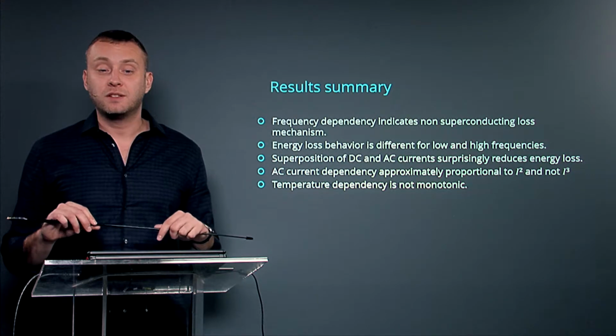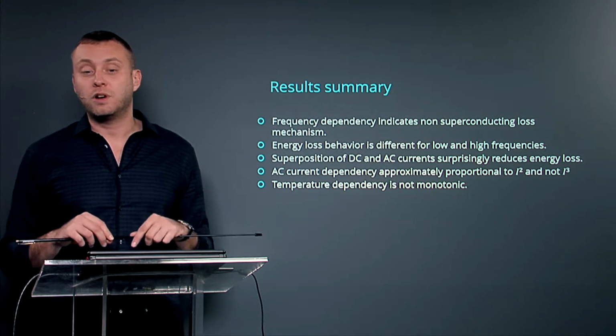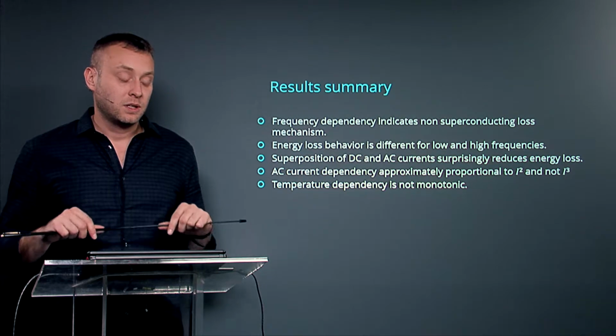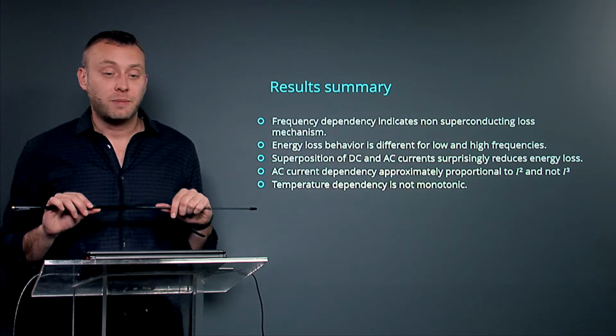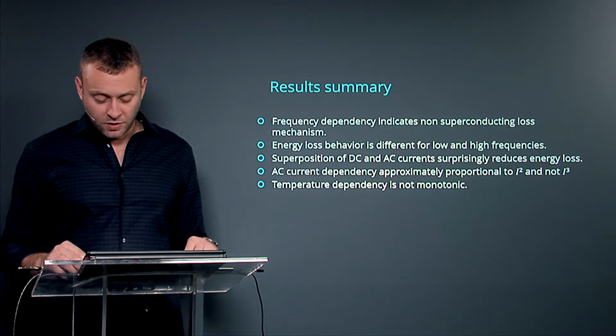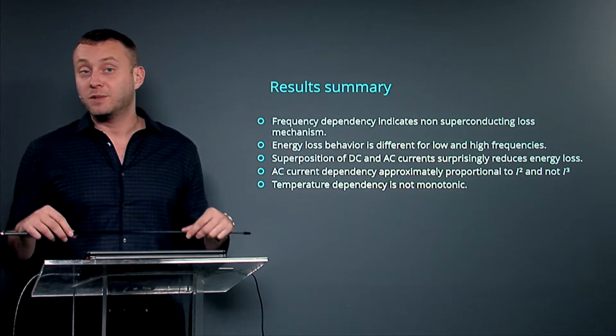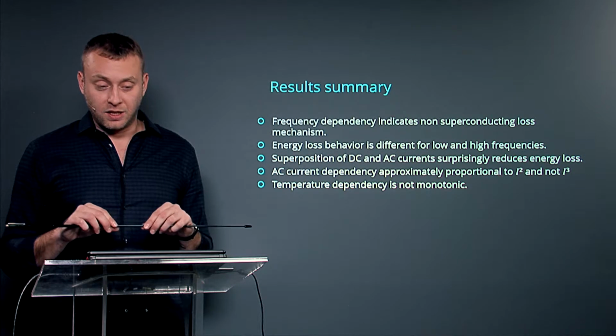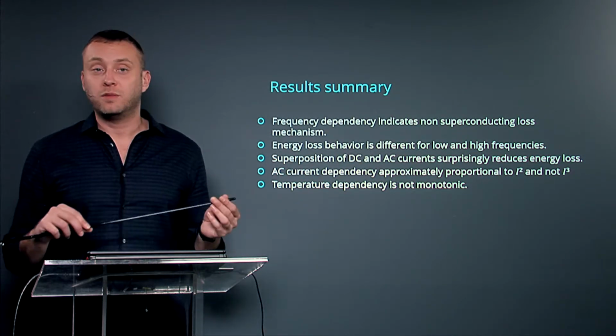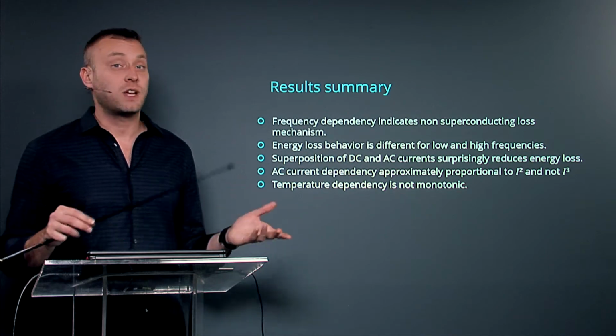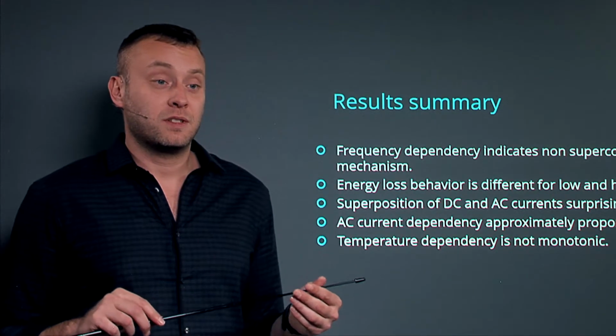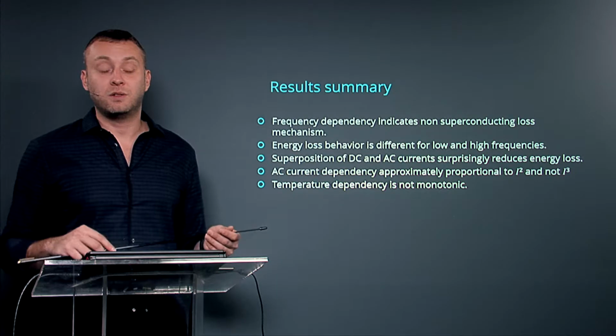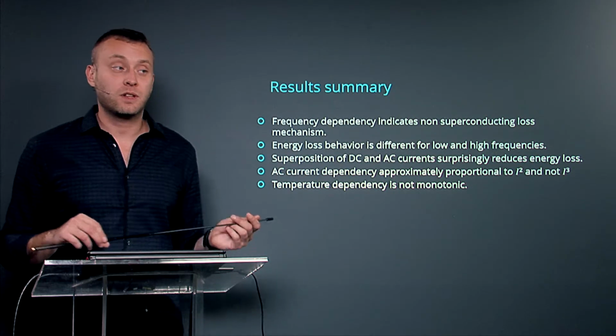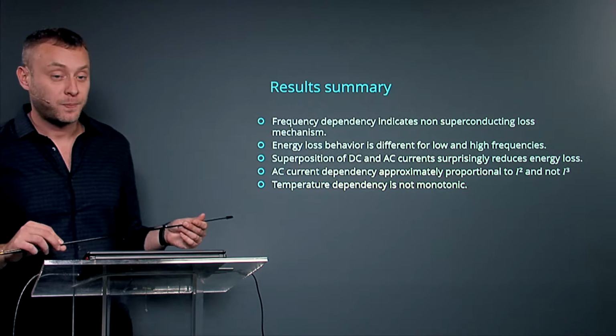The AC current dependency is approximately proportional to I square and not I cubic, and the temperature dependency is not monotonic as well. So we have a lot of things that are not as expected during our experiment design. Are they coming from the wrong design, wrong measurement, or is it a true experiment that there is some additional phenomena that we didn't take into account?